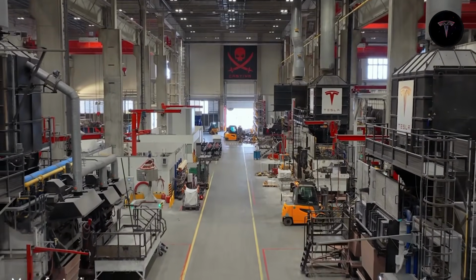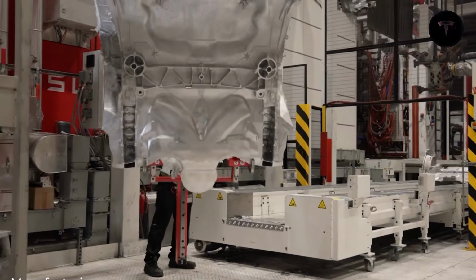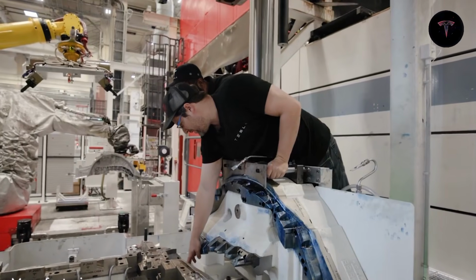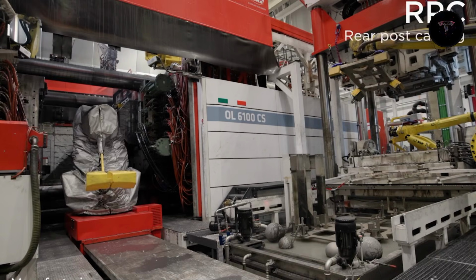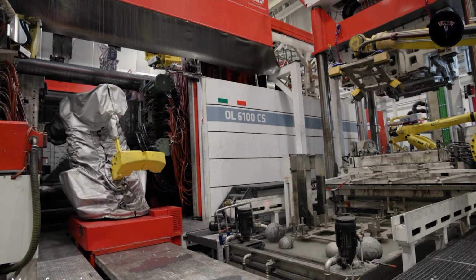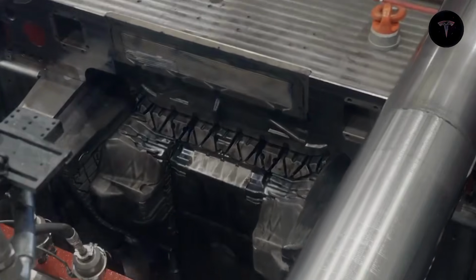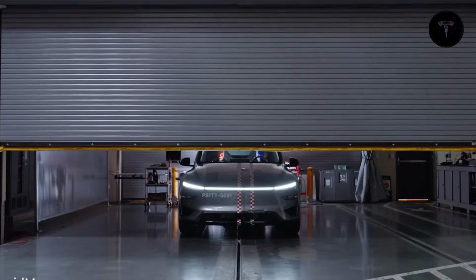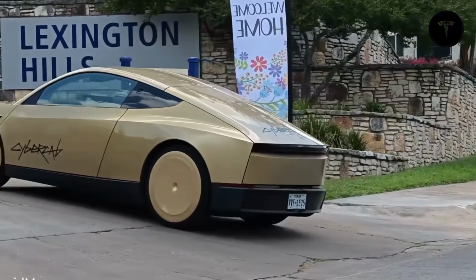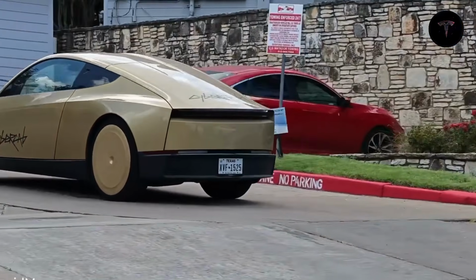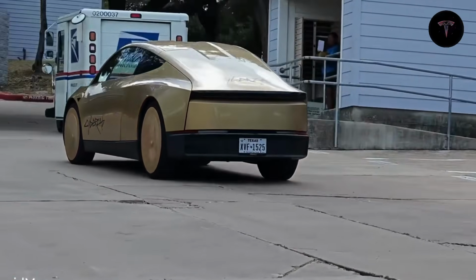The freshly cast part exits the mold at approximately 400 degrees Celsius and is immediately transferred into a cooling bath that drops its temperature to around 50 degrees Celsius. That rapid quench is not only about cycle time, it also influences the metallurgical properties of the finished aluminum, affecting hardness and the distribution of internal stresses.